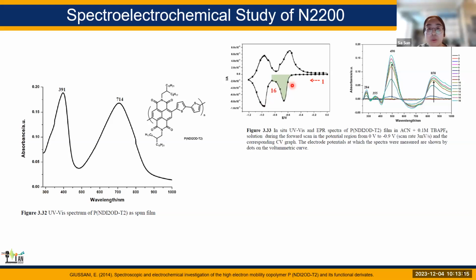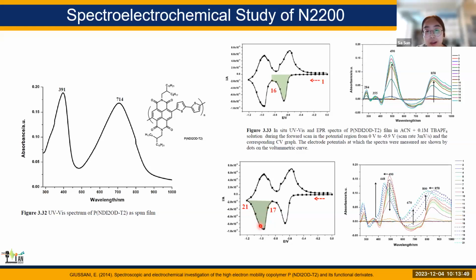And to better study what is assigned to these two reduction peaks, they did the potential dependent absorption spectral measurement. So here shows the difference absorbance spectrum. Once the first reduction happens, they saw a decrease in the original peak of N2200, and they see growth in the 490 and 860 nanometer peaks. And in the second reduction peak area, they saw the decrease in these two previously growing peaks, with a blue shifted shoulder for both peaks.